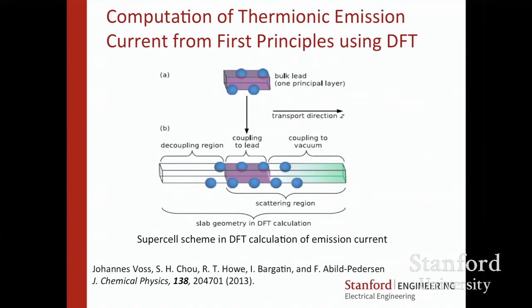In this case, you have a bunch of people. Johannes had the idea that he could cleverly extend the boundary conditions, including the leads, and compute the emission current for the first time. For the very first time, from first principles, compute the Richardson-Dushman coefficient. And I think as we have envisioned new materials, you now have a platform where you can compute work function and the emission current. And so with some serious attention, and of course it's nice to have one of these computing clusters at SLAC that has a lot of cores, thousands and thousands, we put them to good use.